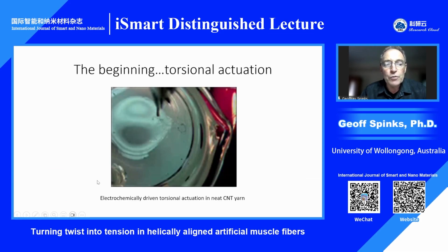And what he observed was that in addition to passing current, the nanotube yarn started to move in the liquid. In fact, it was moving in a fairly controlled way, and it was rotating. And what was particularly interesting was that the direction of rotating correlated with the direction of the voltage scan. So here's at the top left, rotating in the opposite direction. So as the voltage was scanned anodically, it would rotate in one direction, and then as the voltage was scanned cathodically, it reversed that direction.